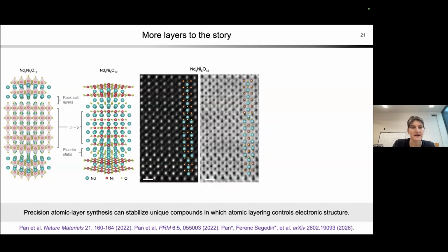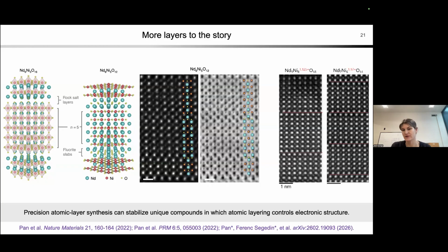With very advanced layer by layer synthesis by molecular beam epitaxy, instead of doping these materials through a chemical substitution, you can just dope them through structural control of the lattice. What you see here are 5-layered versions of those materials. It's basically 5 layers of what I've shown you, separated by a spacer and then another 5 layers. And you can tune that 5 to other numbers. Here you also see an 8-layer version or a 6-layer version. We're working on understanding how these materials relate. They seem electronically similar to the ones I've just talked about, but they might have different signatures of dimensionality. As you confine the properties into those thinner and thinner layers, you can sometimes get other interesting effects that emerge. That's one of the things we've been working on lately.